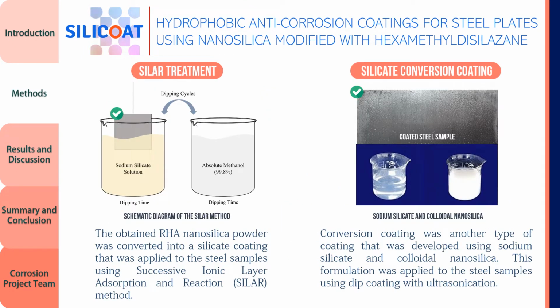The obtained RHA nanosilica powder was converted into a silicate coating that was applied to the steel samples using successive ionic layer adsorption and reaction method, or SILAR. Conversion coating was another type of coating that was developed using sodium silicate and colloidal nanosilica. This formulation was applied to the steel samples using dip coating with ultrasonication.